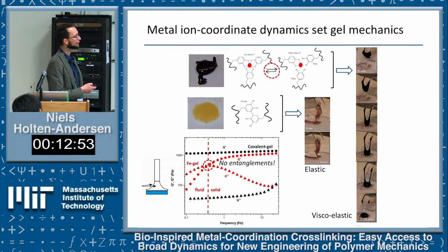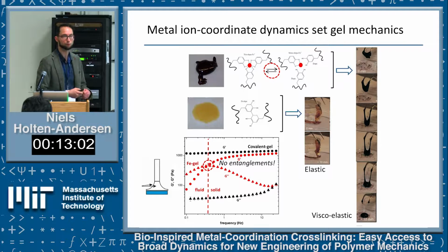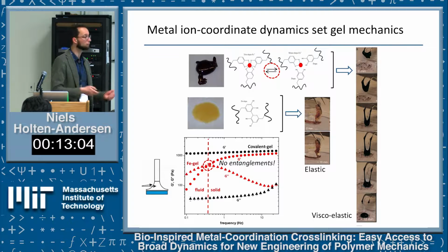If you use the same polymer, and instead of cross-linking it with metal ions, you actually give it a covalent crosslink in the network, you also get a gel, but you get a little piece of rubber. It's a hydrogel, but it doesn't flow like this one. It's not viscoelastic like silly putty. It just behaves like a little piece of rubber.